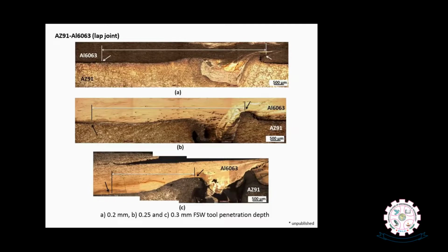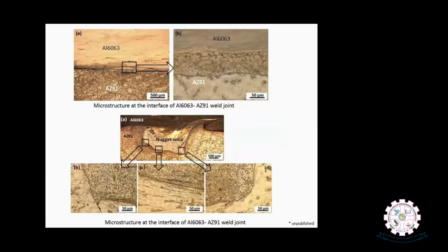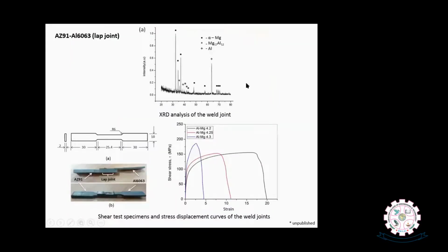actual pin length. And in the successfully produced joint at the interface, we can find the formation of different phases between the magnesium and aluminum alloys, where these phases were examined by XRD, as shown here at the bottom. Also, you can see in the nugget zone a combination of magnesium and aluminum regions. These phases were examined by XRD, and were identified as aluminum magnesium intermetallics. And the samples were tested for the mechanical properties.